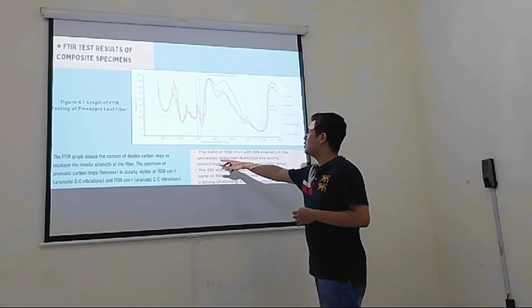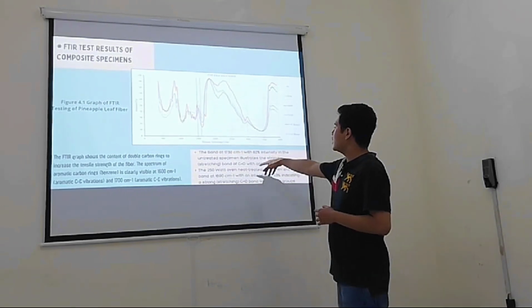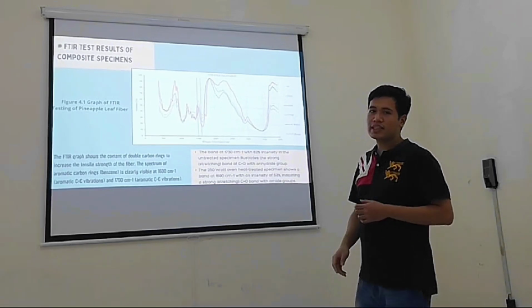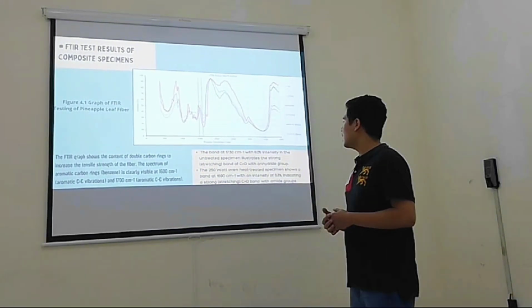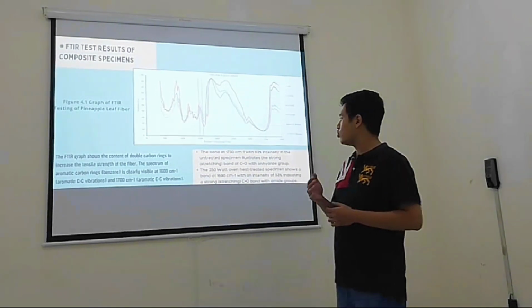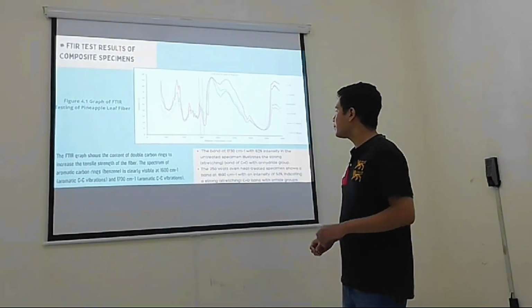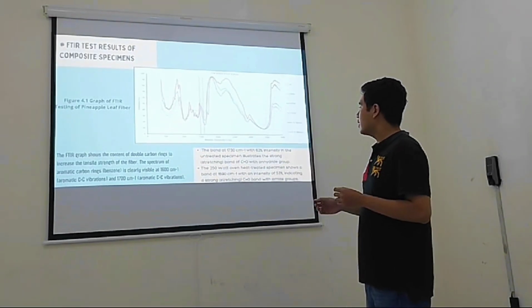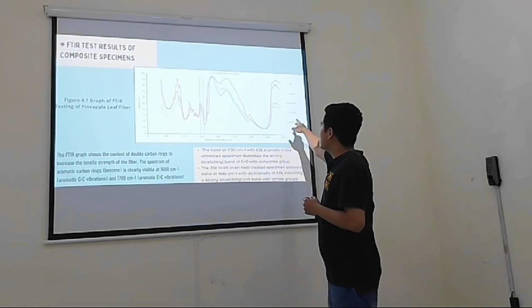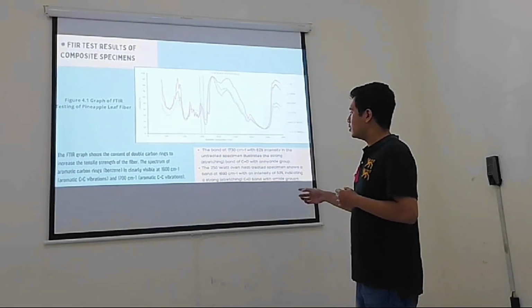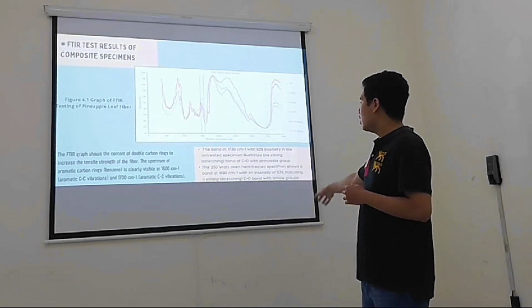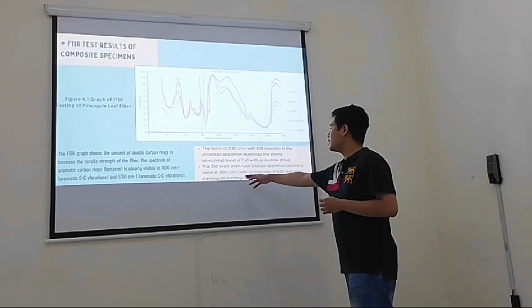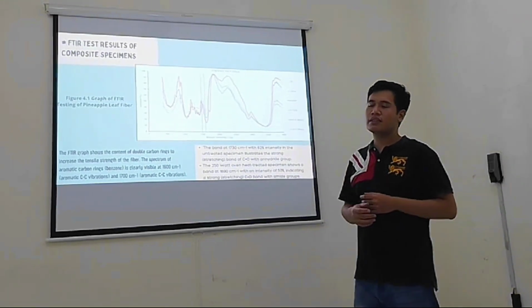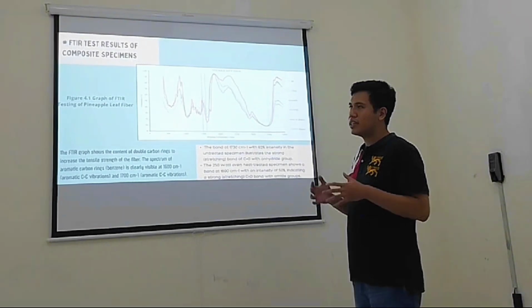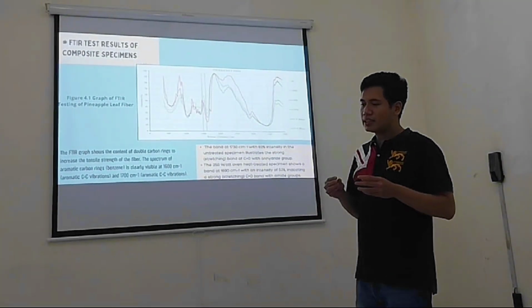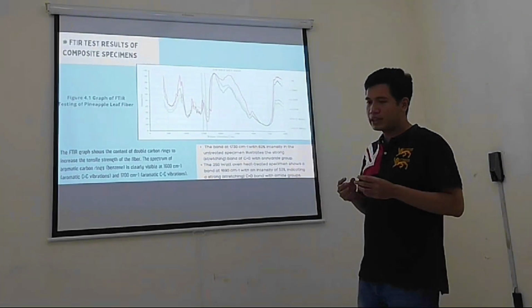As you can see, the band with 62% intensity in the untreated specimen illustrates the strong stretching bond of C=C. As you observe, the specimen at 250 shows the band with an intensity of 53%, indicating a strong stretching carbon and oxygen bonding with amide groups.